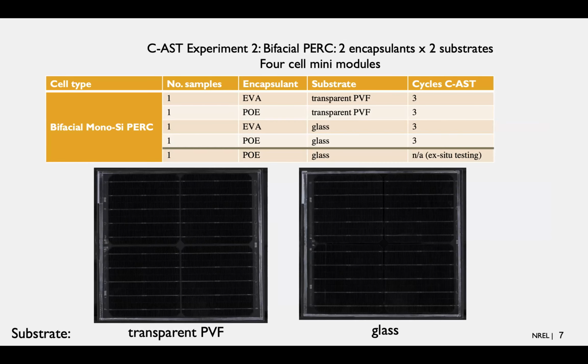Okay, I'm going to shift gears to move to our second experiment, and this involved bifacial PERC cells with 2 encapsulants and 2 substrates. So we had 4 cell mini modules again, and the details of the experimental matrix are shown here. We had encapsulants of EVA and POE, and we also had transparent polyvinyl fluoride rears and glass rears or substrates. And all of these went through 3 cycles of combined accelerated stress testing. We also did some ex situ experiments, and I'll walk you through those. And here we're looking at the pictures of the modules.